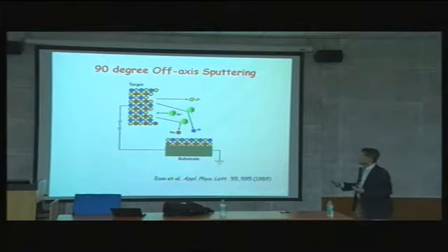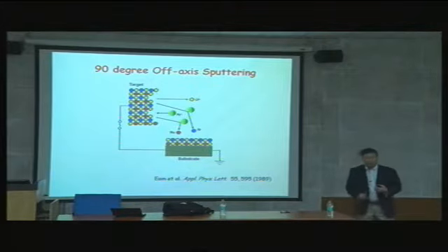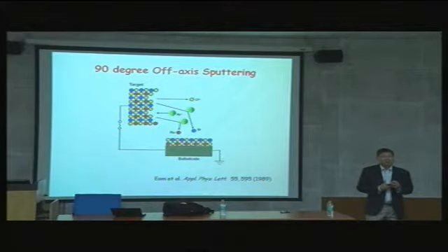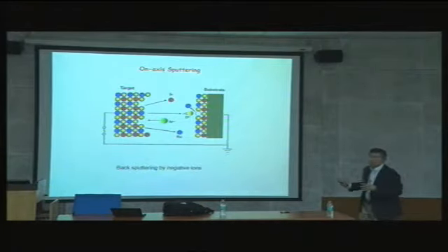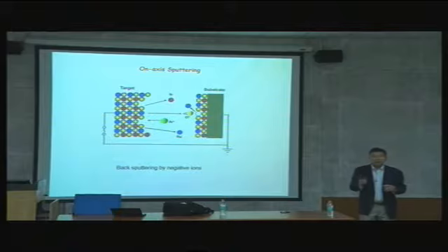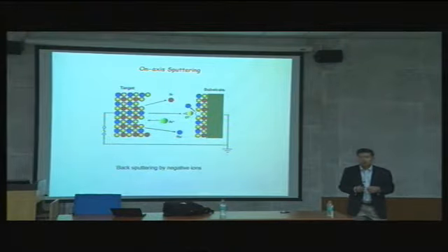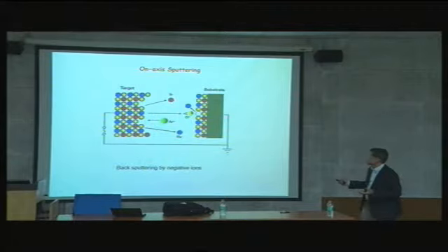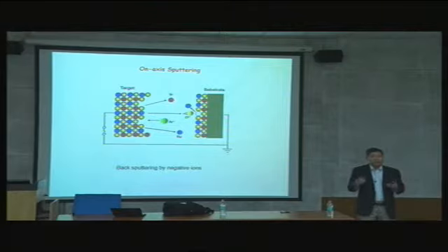So this is called 90-degree off-axis sputtering, and this is the first geometry I tried. It has been many years with this geometry. Every time I grew these superconducting thin films, they were not superconducting, or they were insulating, because the stoichiometry was not correct. The problem with this one is the oxygen here. It doesn't sputter all of them. It back sputters selectively.